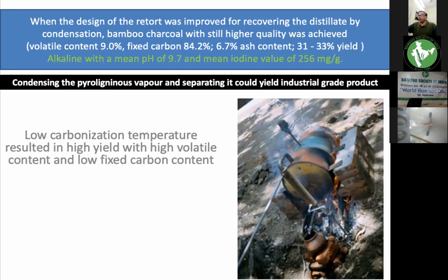That means when we used the pyroligneous gas for heating, and when we condensed and collected the pyroligneous gas, the quality of charcoal was much better. A low carbonization temperature resulted in higher yield with high volatile content and low fixed carbon content. Again, a close-up view of the single drum retort system with facilities for condensing the gas and collecting the distillate is shown here. This is appropriate to the rural context. So this is what we obtained. Can we go to the next one?